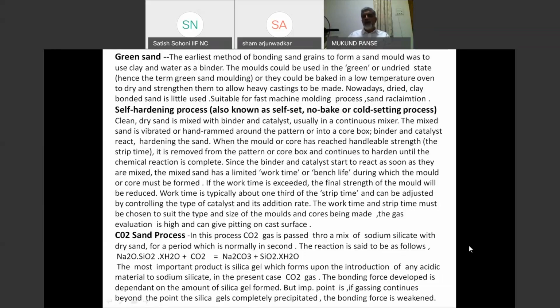The second most common use is the self-hardening process, that is the resin self-set process. Here again there are hot and cold processes. Hot resins are shell molding or hot box, and for cold there are a number of different combinations. The resin and catalyst are mixed and coated on the sand grains, normally in a continuous mixer. The sand is dropped on a molding box where the pattern is kept and it is rammed. As soon as you coat the sand with resin and catalyst, the reaction starts and the sand starts setting. However, you have to make the mold before the sand gets set so that you are able to ram the sand properly. This is called the work time or bench life of the no-bake sand.